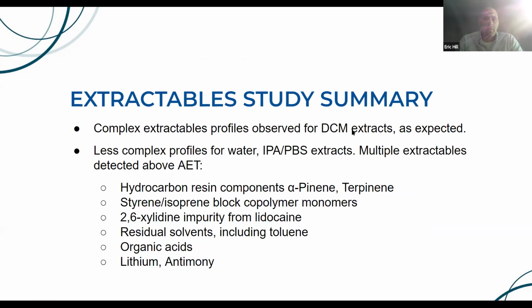Once we executed that analysis, the summary of what we saw: very complex extractables profiles from the dichloromethane extracts. As we would expect, dichloromethane is a very powerful extractant. We had less complex profiles for the water and the IPA PBS extracts. Multiple extractables, however, were detected above the AET. As expected, and as we documented, we saw hydrocarbon resin components, including alpha-pinene, terpinene. We also saw styrene, isoprene, block copolymer monomers, several of those.